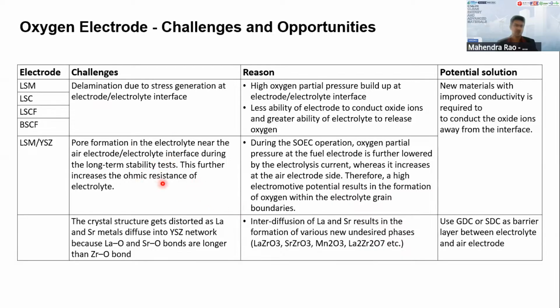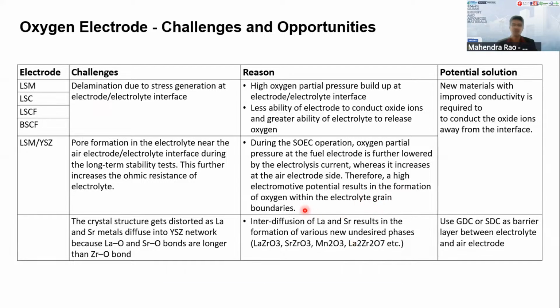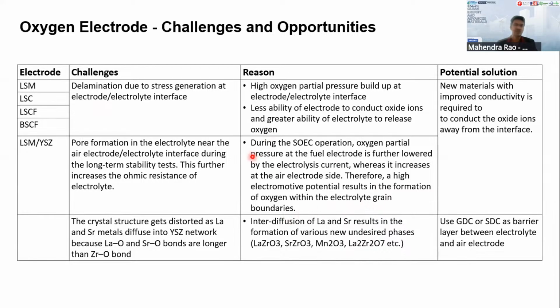So the stress generated between the electrolyte can delaminate the electrode from the electrolyte. And then pore formation. So we know during SOEC operation, oxygen partial pressure at the fuel electrode is further lowered by the electrolysis current, whereas it increases at the air electrode side. Therefore, the high electromotive potential results in the formation of oxygen within the electrolyte grain boundaries. So this will cause the formation of pores in the electrolysis cell.